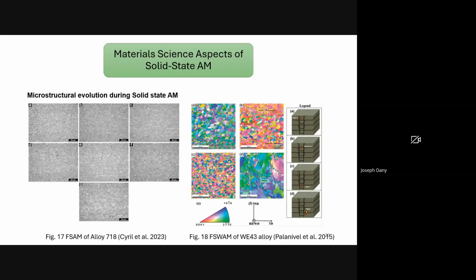However, these microstructural differences between layers typically do not translate into significant variation in mechanical properties, unlike fusion-based additive manufacturing. The key reason is that solid-state additive manufacturing processes avoid melting and resolidification, which are primarily responsible for common defects and heterogeneity in fusion AM, such as porosity, hot cracking, and segregation.